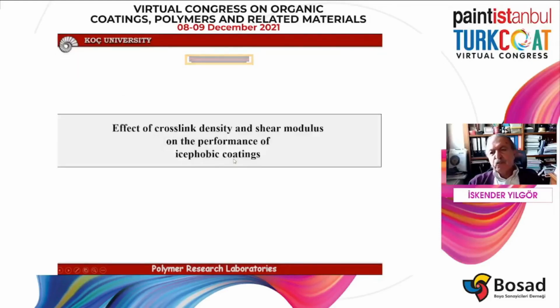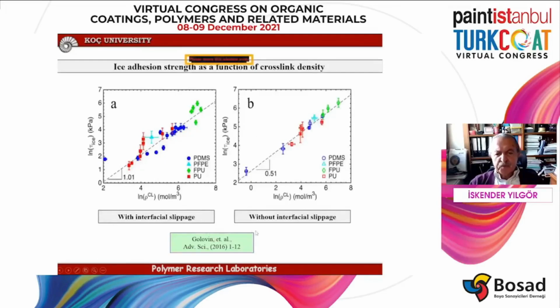So the best thing is to be able to make just a simple thermoplastic polymer and coat it. Now, finally, there is a lot of work on the effect of crosslink density and shear modulus. And here, this is a big group in Michigan where they have shown that either by using silicone or fluorinated polymers or polyurethanes, depending on the crosslink density, which is the x-axis, the ice adhesion strength changes. So if the crosslink density goes down, if you form soft surfaces, then you will have low ice adhesion. This is logarithmic. So it's not 1, but actually this is about 10, this is 100.